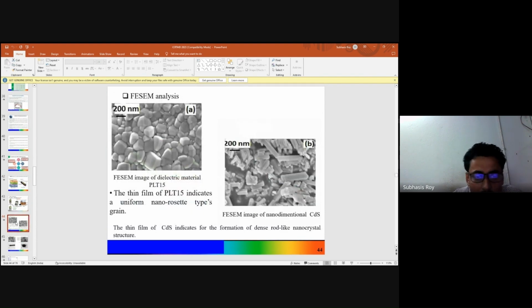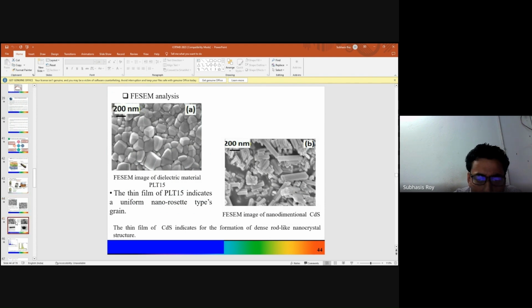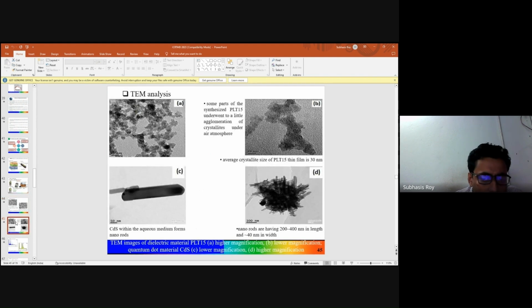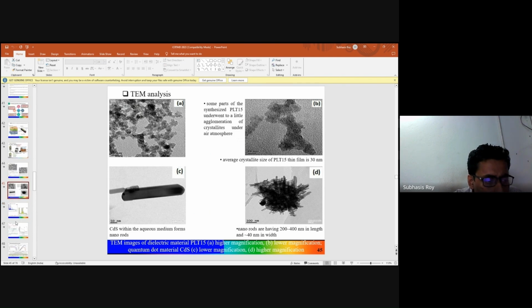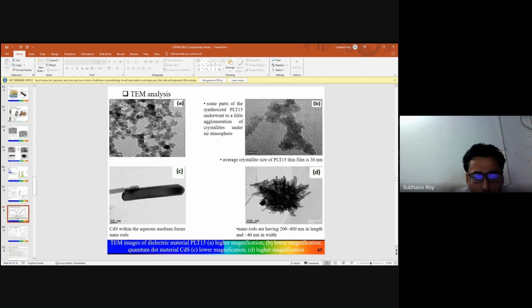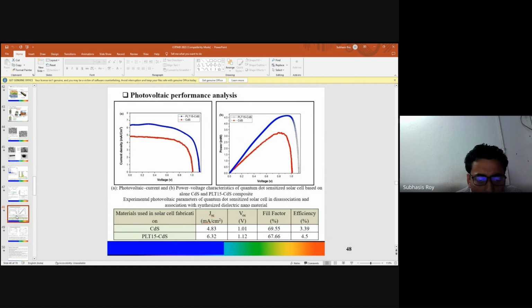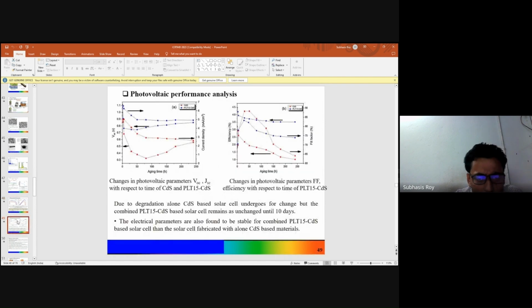So here is the difference in structural morphology with the dielectric material in the solar cells. We have done TEM, where a nanostructure, nanorods, is coming up in the systems. Here, if you see the analysis with the dielectric material, it is giving higher efficiency, and the stability is much more increased. It is much more stable compared to what I initially reported. Around one month, it is much more stable.